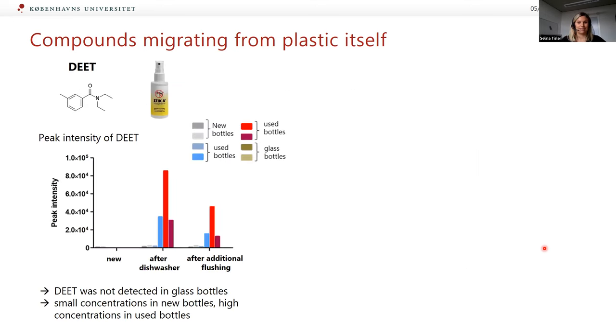Another example of what we detected is DEET. DEET is known as an insect repellent in almost all insect repellents which are used. And we saw it not in the new bottles, but in the used bottles. Depending on how brittle the material was, we assume that was the main reason why there were differences between the bottles. There we saw high peak intensities of DEET. Now the question is, why is there an insect repellent in the plastic bottles? When you read about the use of DEET, it also says don't use it when you wear a watch, for example, because it can attack the material. And digging more into the literature, we also found a study postulating that DEET can be used as a plasticizer itself.